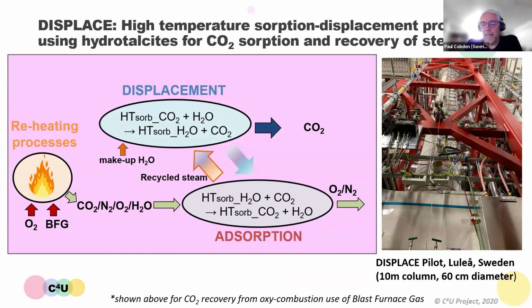Here you see on the right-hand side, this is called the displaced pilot. It's a 10-meter column, 60 centimeter diameter. It's filled with a material called hydrotalcite, which is an anionic clay operating at 400 degrees C. Normally, we'd use that in a PSA type of mode, but in previous projects, we found out that there was also a mechanism that occurred on this material called displacement. And so we could use that to create blocks of CO2 and steam that move through the column.